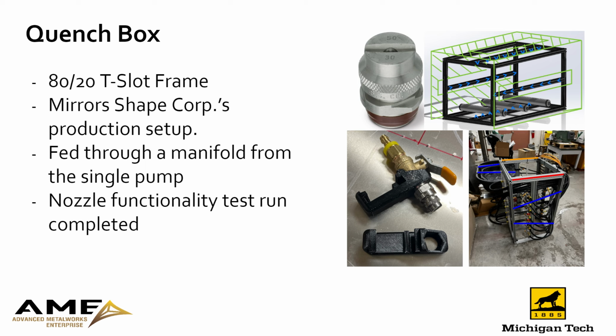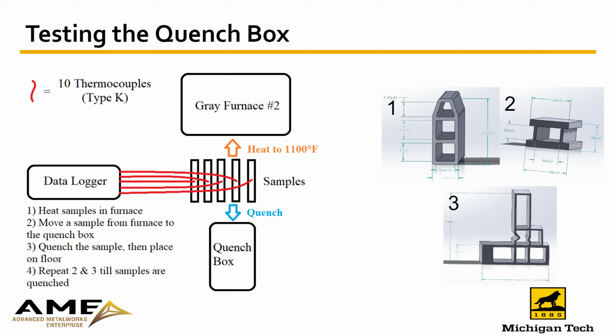With the furnace all set, the next step was the quench box, which we built out of 80/20's T-slot framing aluminum, which mirrors ShapeCorp's actual production setup using their specific nozzles supplied by Granco Clark. The water is fed through a single manifold system that splits out to all 30 nozzles, which are then held in place by 3D printed brackets. We also completed a nozzle functionality test to make sure that the system itself works.